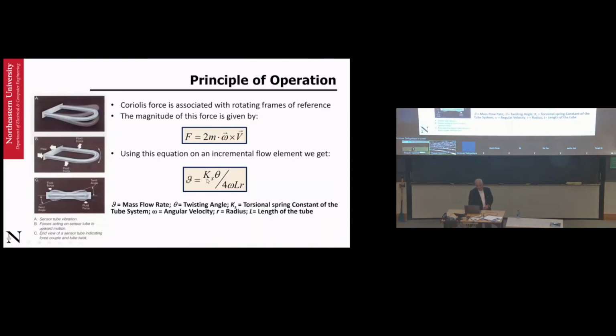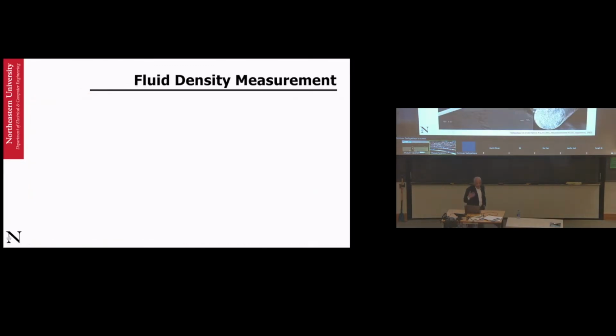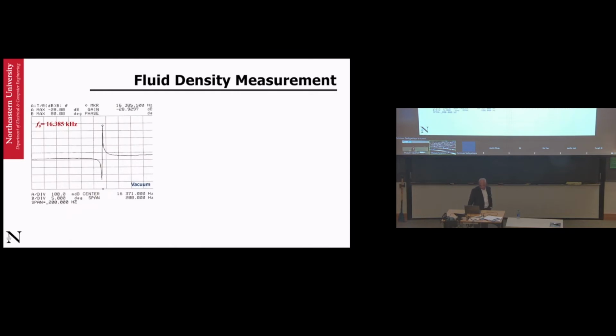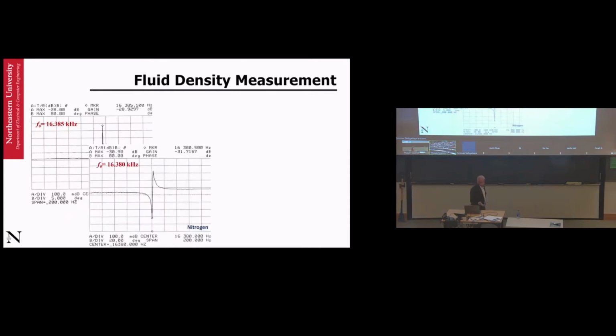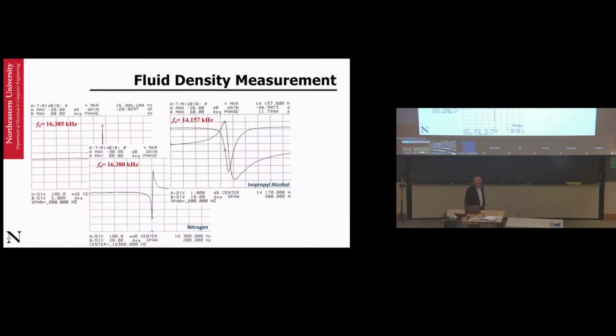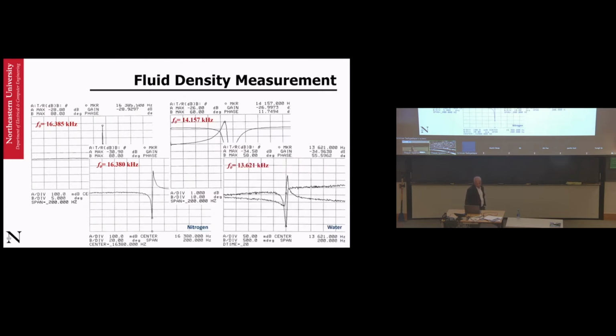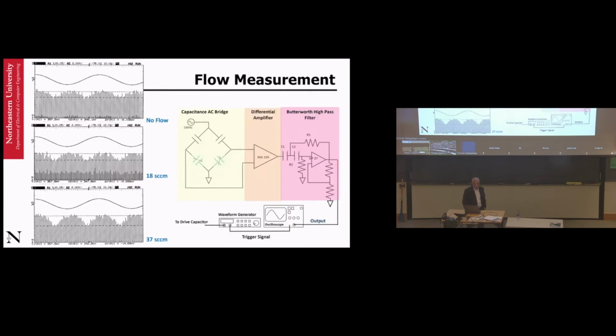You look at it from the twisting angle, the mass flow rate, not the number of molecules or anything like that. I'll just show you some results here. I don't want to dwell too far on it, but as you start filling in different fluids, you can see that the frequency starts to shift, which is exactly what you expect. Then, of course, you have to create an interface circuit, which later on became much better, but you can start seeing the size of these capacitors.